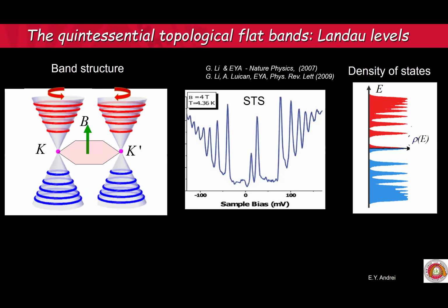So this is an example of Landau levels in graphene. Here we have the two K points. They're related by time reversal symmetry. You apply a magnetic field, you slice the band structure, and you get these beautiful Landau levels. The energy sequence goes like the square root of the Landau level index and magnetic field, as opposed to linear, just because of the linear dispersion. And these are STM pictures, and this is what the density of state looks like, electron sector, hole sector.